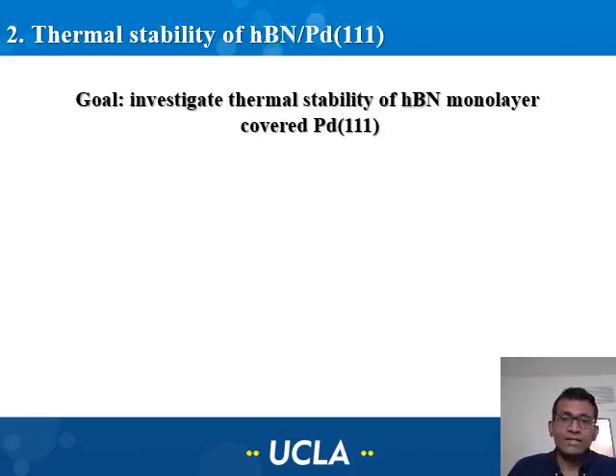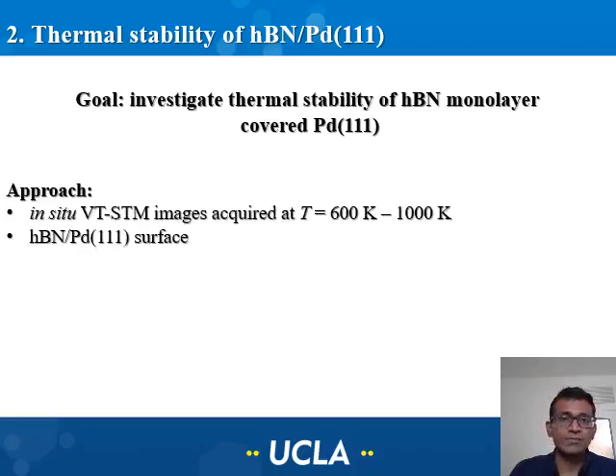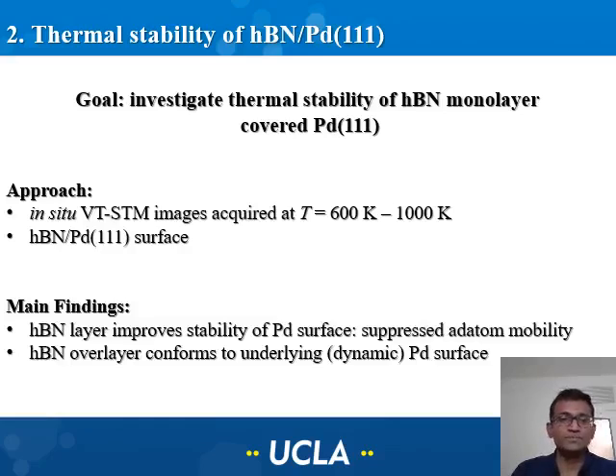And so with that in mind, we focused on understanding the thermal stability of a monolayer of hexagonal boron nitride on palladium-111. What we did is carry out in situ variable temperature scanning tunneling microscopy studies, and we obtained images while scanning at temperatures up to 1000 Kelvin, using hexagonal boron nitride covered palladium as our surface.